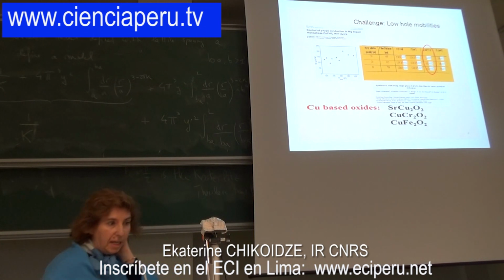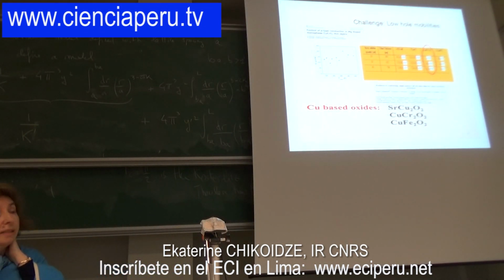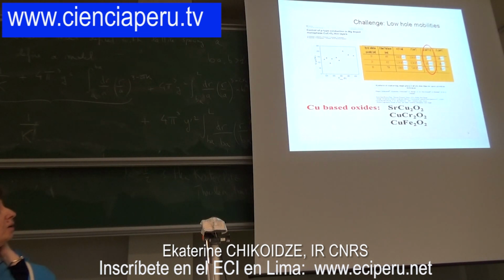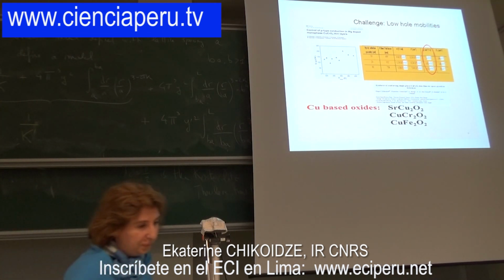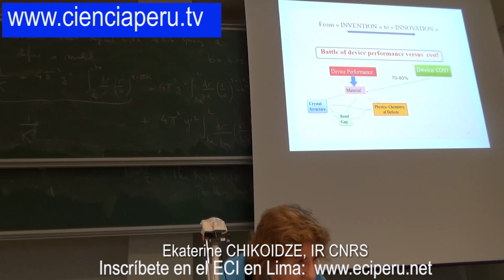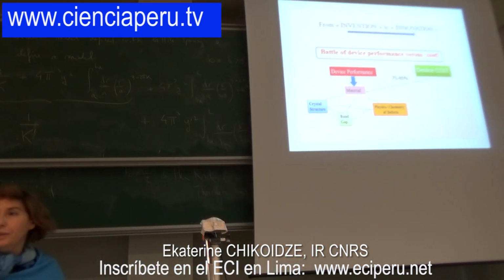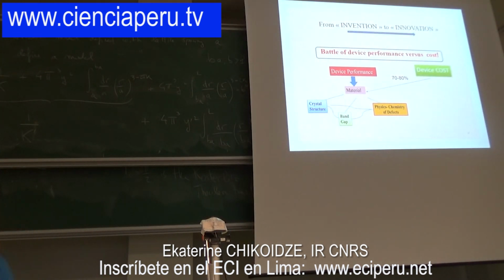And the second example, transparent conducting oxides which are P-type. Also here the difficulty is not so much resistivity but very low mobility, which needs special instrumentation and special methodology to apply. And so we have this possibility to measure very low mobility, below 1, and to extract correctly the value of mobility. So that was just briefly to tell you which kind of materials we are working on.